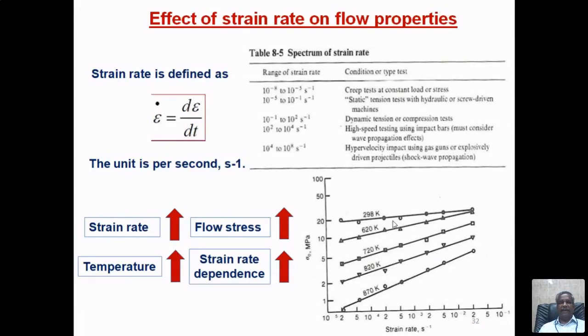Okay. Please. The strain rate, as I told you at the beginning, we are fixing the strain rate when we do the tensile test also. See here, the table is not so clear, I don't know. The range of strain rate is given, 10 power minus 8 to 10 power minus 5. Okay, the creep test, we'll discuss in the last lecture, where I plan to give creep behavior. The creep test is a very, very slow test, will take a longer time.